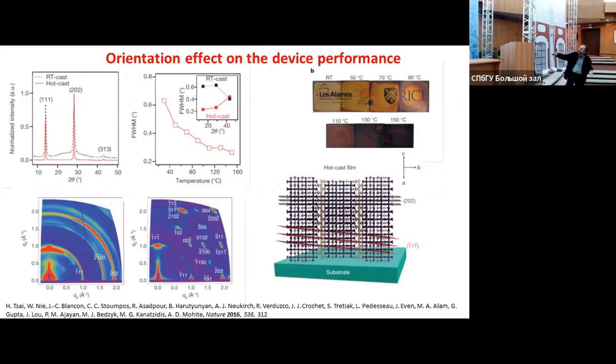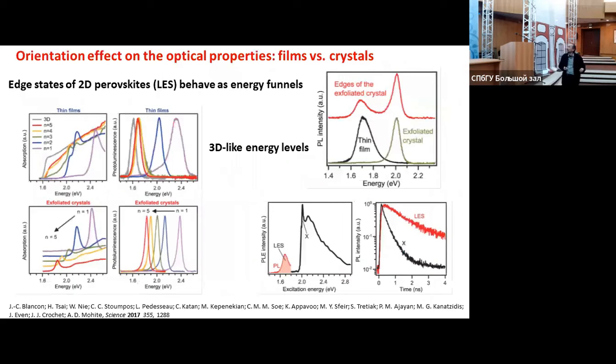And this is the picture that we want you to imagine. But by GIWAXS experiments, we actually show that the method is important. When you are able to grow large grains of the material on the film, you are able to get high efficiencies as opposed to the polycrystalline film here. And another effect that we saw, we didn't name it or address it at this time, but we address it later on.